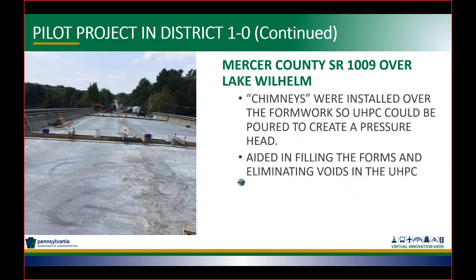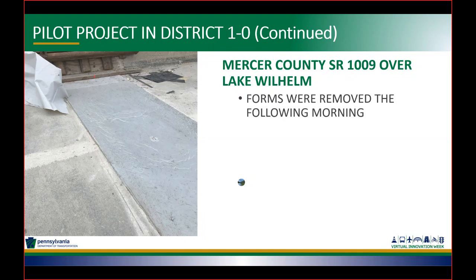This is a photograph of the finished formwork after the UHPC had been placed. We actually had to use chimneys to provide kind of a pressure head, if you would, where they were pouring the UHPC down through those buckets that they had cut holes in the bottom of, to actually force the UHPC to flow through the form and to get up to that quarter inch higher than the adjoining deck elevation. What you're looking at here is the following day after the placement of the UHPC. As you can see, there is a lip there where we were successful in getting that quarter inch reveal of the UHPC higher than the adjoining deck elevation.